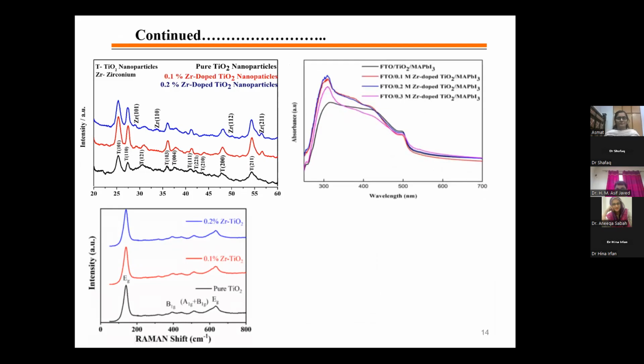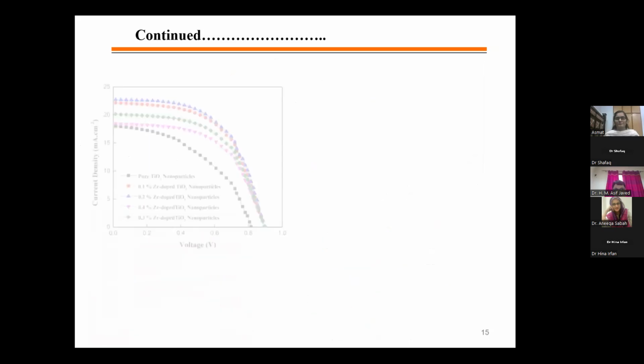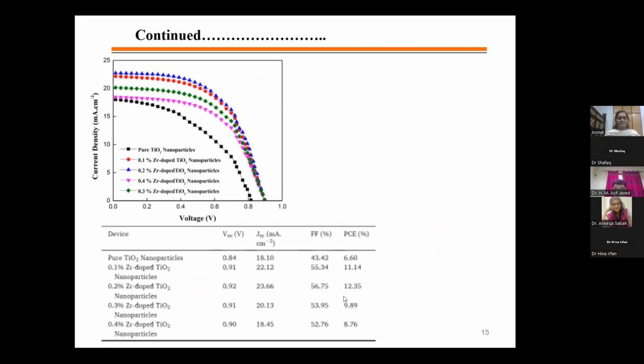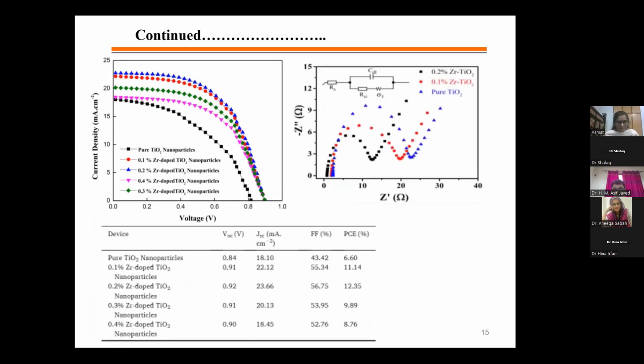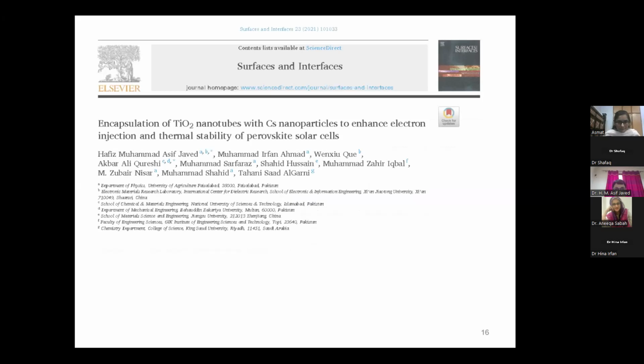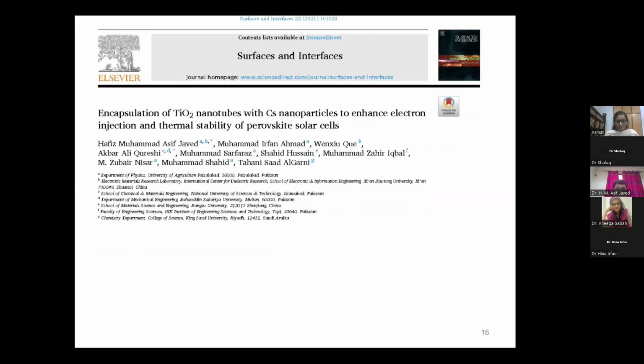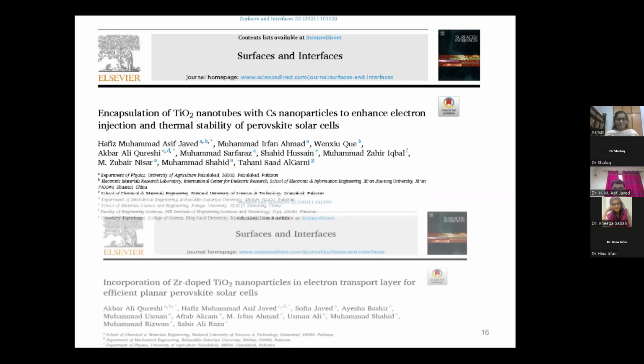Absorption spectra have been conducted, and we can see from here 0.1 molar, 0.2 molar, and 0.3 molar different concentrations. We have conducted the experiment to optimize the concentration of zirconium, and after that we have achieved the results. We can see from here the high efficiency of 12.35% with the 0.2% zirconium-doped titanium nanoparticles. Electrochemical impedance spectroscopy also shows the behavior of the zirconium titanium-based nanoparticles. Both works have been published in Surfaces and Interfaces with these titles. For further details, you can download these papers, and you can also contact me if anyone is interested in this research.